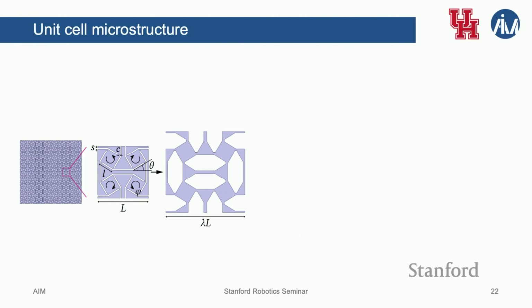And of course, if you change the theta angle, the initial inclination, and the length of the inner square, you can change what this lambda is. So the lambda is the amount of opening you get from the initial unit cell. The initial unit cell is size capital L, the opened unit cell is size lambda times L. And this lambda is the most important bit, because we're going to change the lambda everywhere on the surface. It's not going to be the same. Because if the lambda is the same, you just get a bigger sheet. So if we change the lambda everywhere, we'll get a 3D shape.